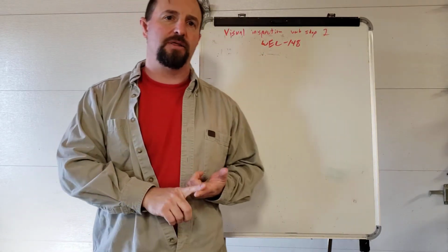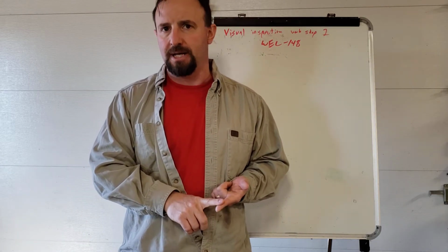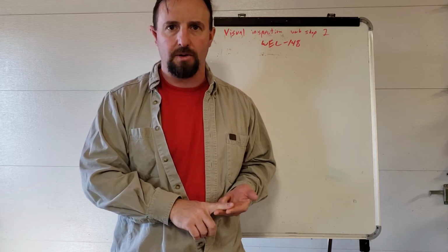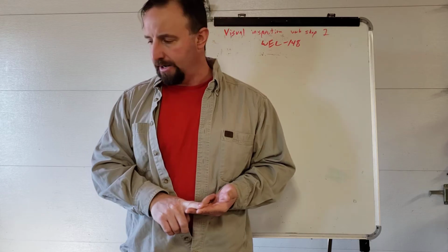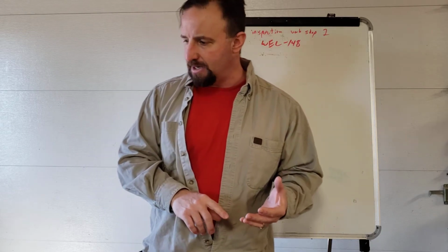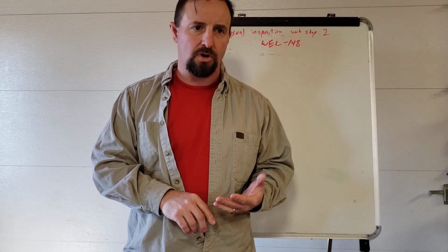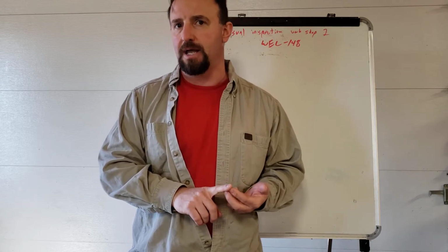If we're seeing this with hardwire type welding, usually that means that we've lost our gas shielding. If we're seeing this with stick welding, it's almost always an indication of long arcing. Depending on the placement and what it looks like, other ways that we're going to see this could be base metal contamination, especially hydrocarbon contamination in aluminum.